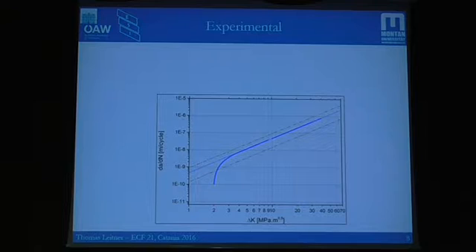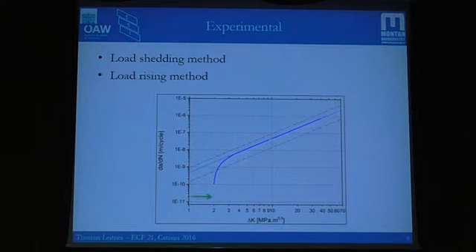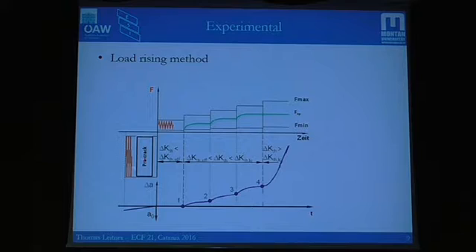For measuring fatigue crack growth, people usually use the load shedding method. We start at quite a high delta K and reduce it until no crack growth is detectable anymore, so we get the threshold value. However, we started at the other side, so we use the load rising method, where we start at lower delta K values. How is this done? We start with a compression pre-crack, as shown here. We then start with low loading forces, where we see no crack extension, as in this region here. We then increase our load amplitude until we see first crack extension, and this point here is the effective threshold.